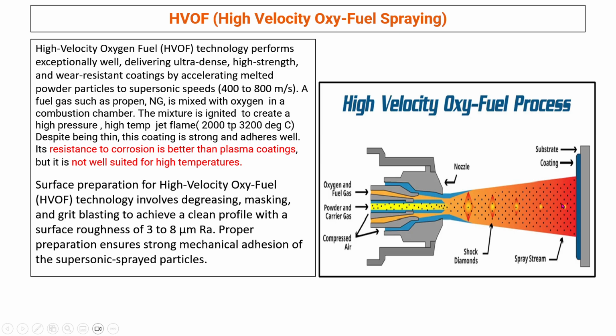But to get a better result, you have to do surface cleaning before this operation. You need to clean the substrate. You have to do either shot blasting or grit blasting, then degreasing, then masking, and your surface roughness shall be 3 to 8 micron. If you get that surface, then the powder will adhere to the surface, and that will give you a wear resistance coating better than the parent material.